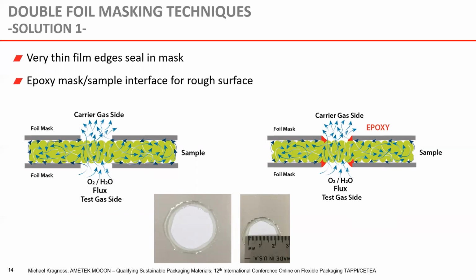So double foil masking can be a good option if you have a thin film. And since it's thin, it doesn't have much edge to it. So the adhesive from the foil masks can actually be sufficient to seal the edges of your thin paper. So when you double foil mask a thin paper, a lot of the times, if the adhesive sticks well to your sample, it will seal off those edges inside of the mask, so you won't get this edge diffusion. So then you can rest assured that all of your flux is actually going through the film and you're not losing driving force.